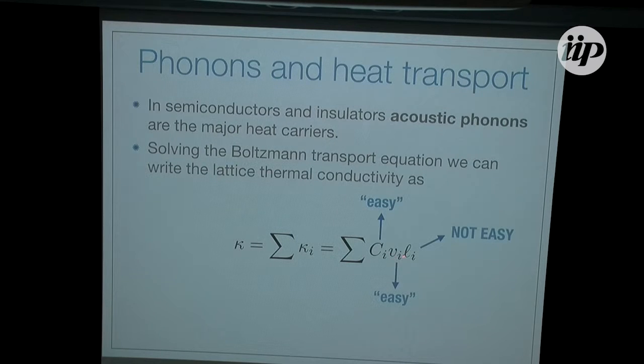Now the difficult part is to calculate the phonon mean free path. All the anharmonic information essentially is in here. This is how long these phonons can travel before they scatter with other phonons. And this is the tough part. There are ways to calculate this, but unless you use fairly simple approximations, it gets very difficult. But there are other ways of calculating the thermal conductivity without actually solving the Boltzmann transport equation.